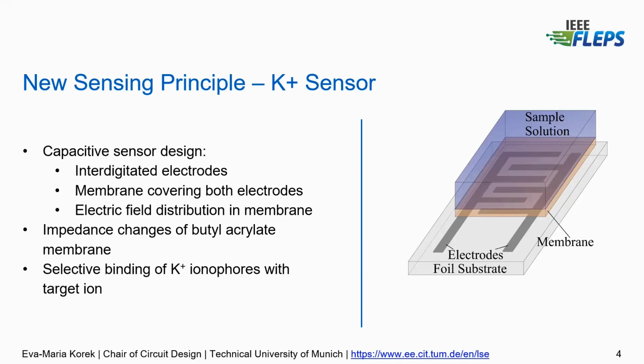And on this foil, we have interdigitated electrodes that are covered by the ion selective membrane. And I think we've heard it a lot today how it works. So we have the potassium ions inside of the membrane. And in our case, we then apply an AC signal, so a voltage across these electrodes, with a frequency ranging from 1 megahertz to 100 millihertz. And we measure the impedance changes of the membrane instead of a potential shift.